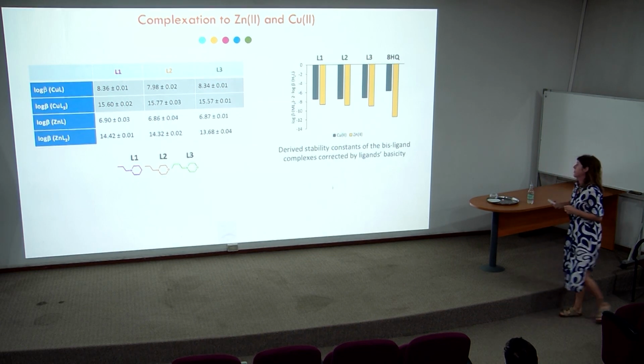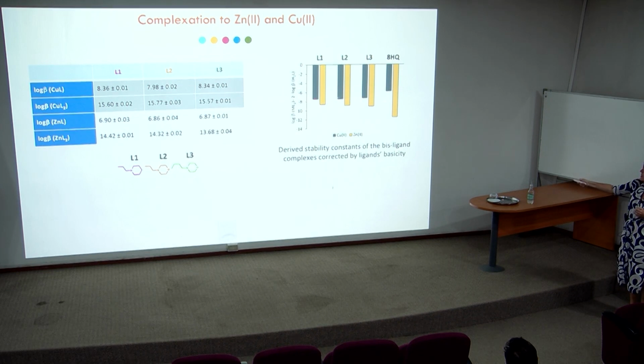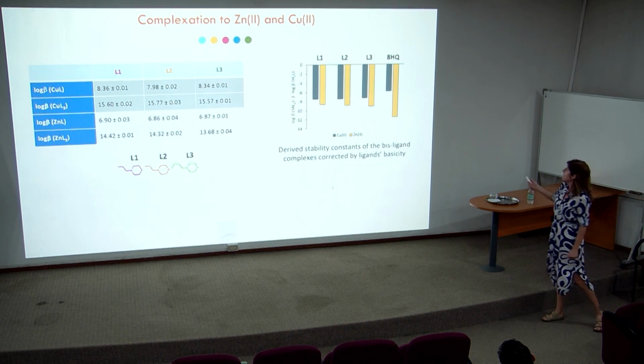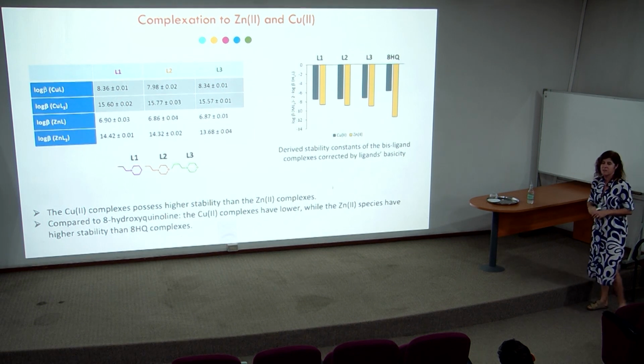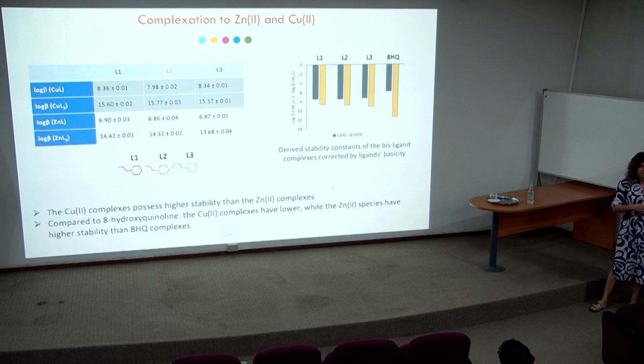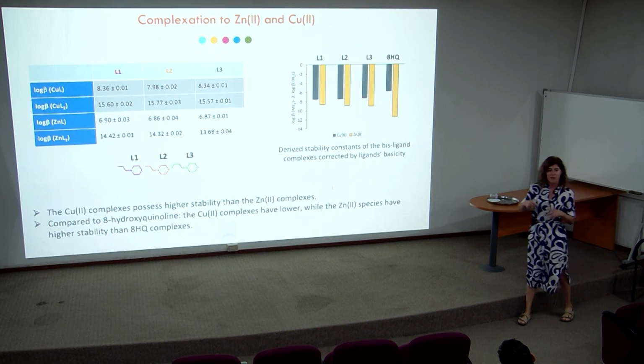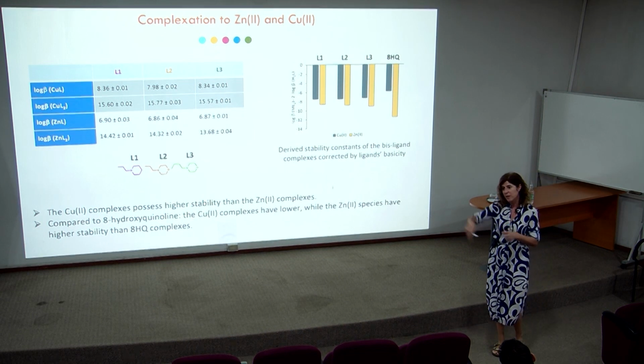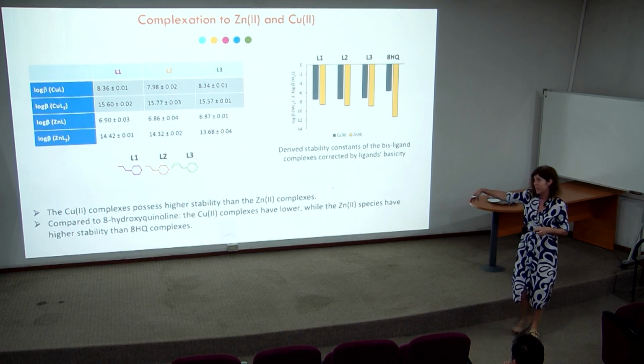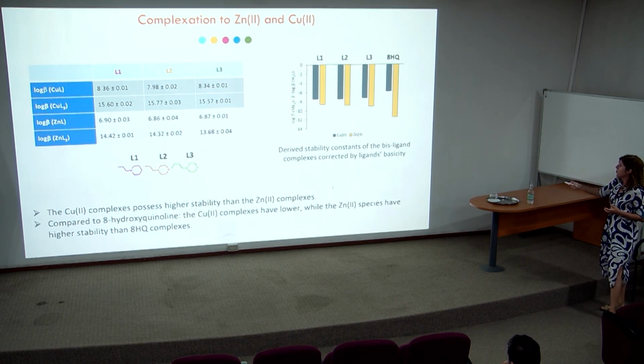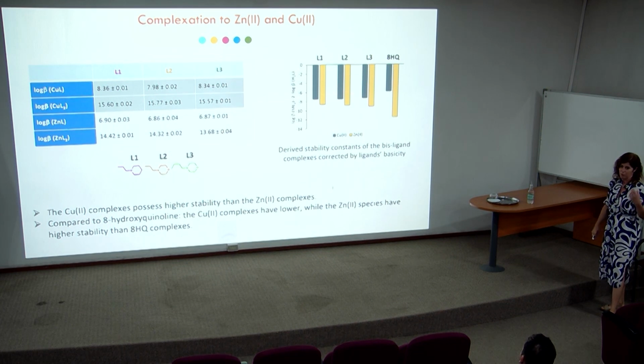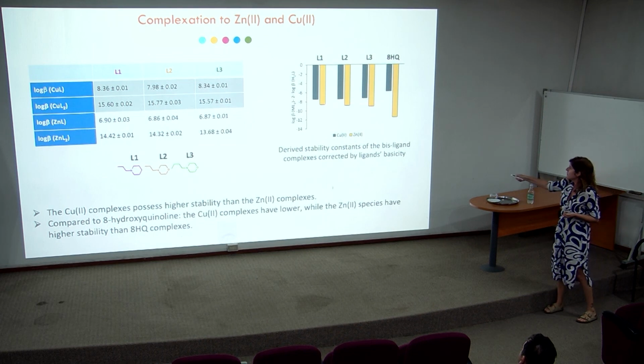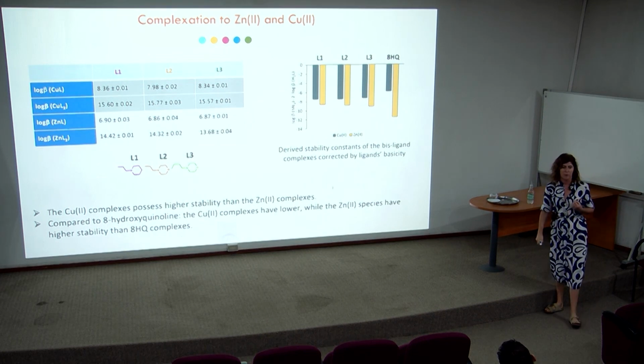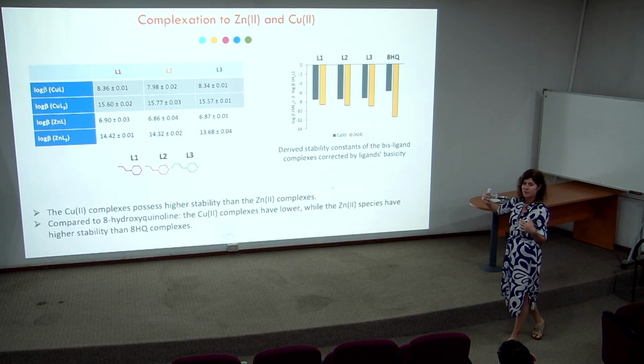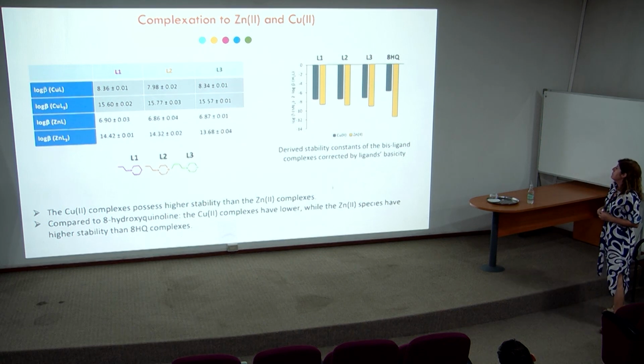And how can we read this? So the higher the intensity of these bars, the lower the stability. So what we could see is that for copper, the complexes are less stable than the 8-hydroxyquinoline ligands. And this makes sense, right? Because the coordination is the same, is through the 8-hydroxyquinoline, and we have a pendant arm that does not participate in coordination. But we can see that the stability of the copper complexes is still higher than the stability of the zinc complexes. But in the case of the zinc complexes, our complexes are more stable than the complexes with 8-hydroxyquinoline because now we have a tridentate ligand. So all of this makes sense.